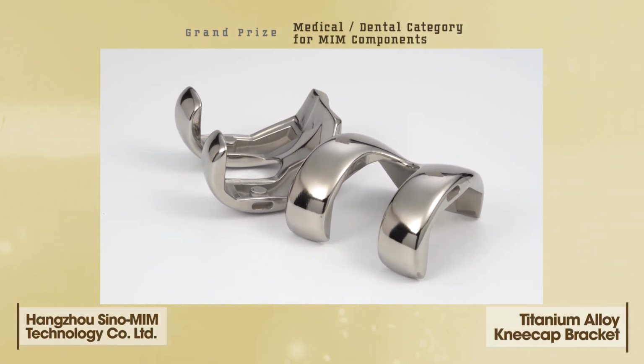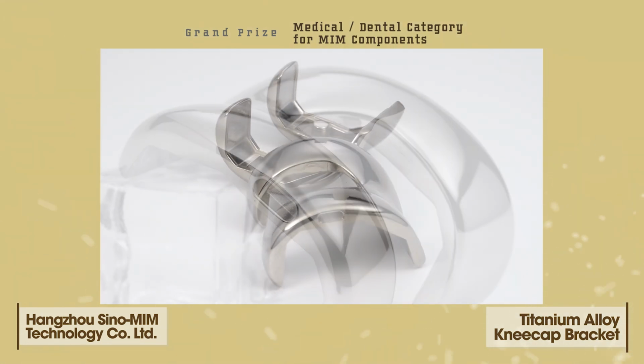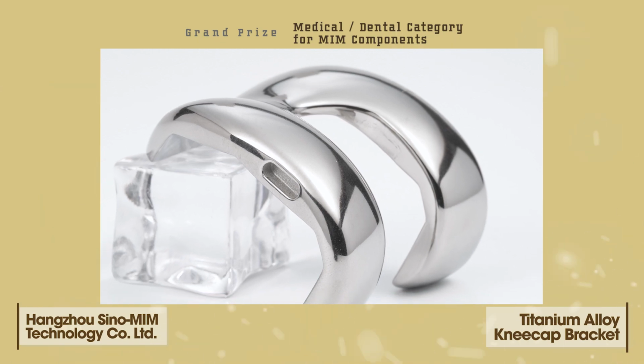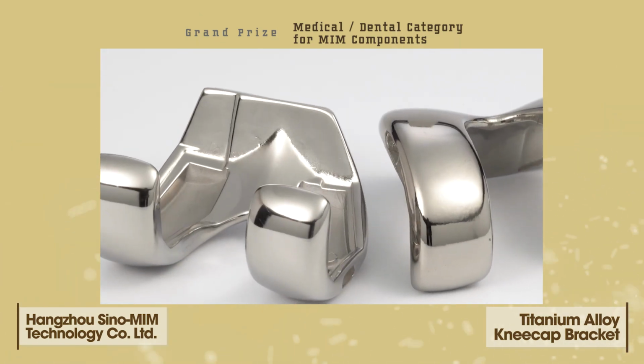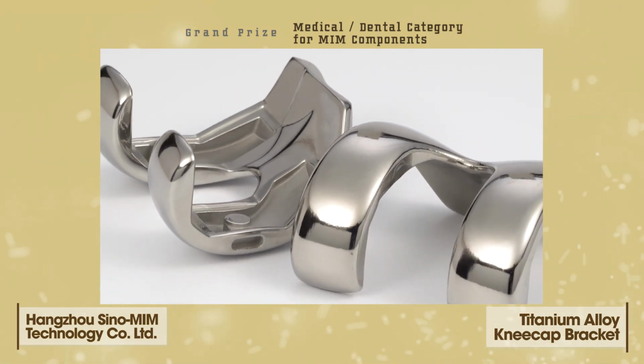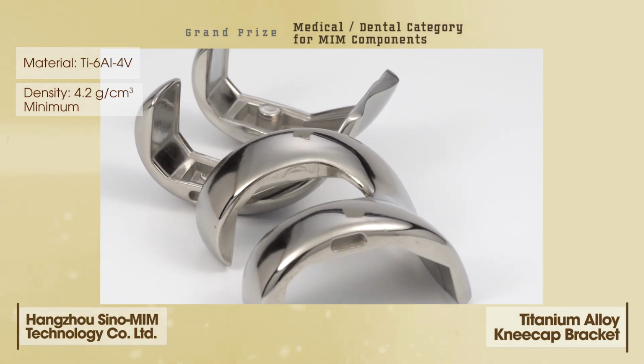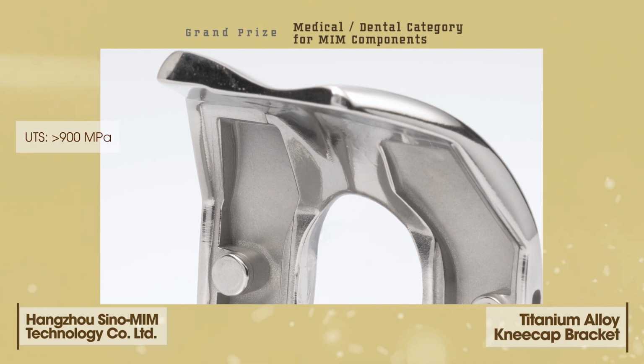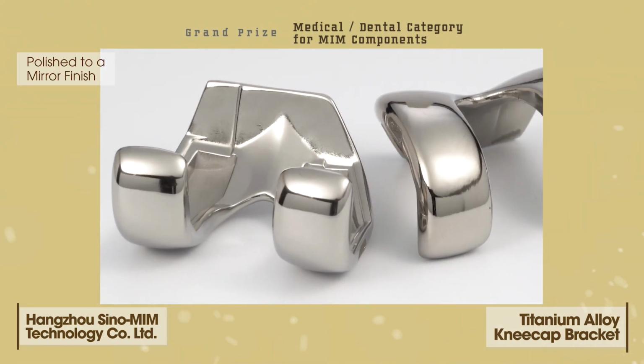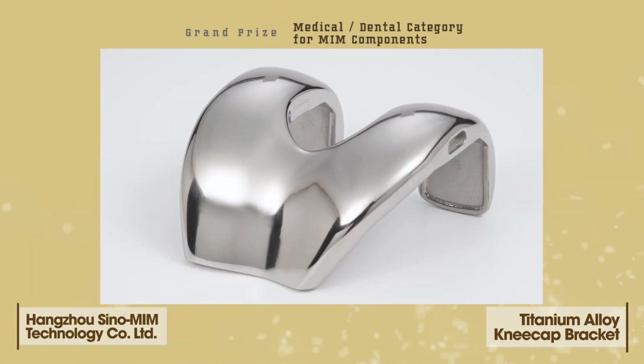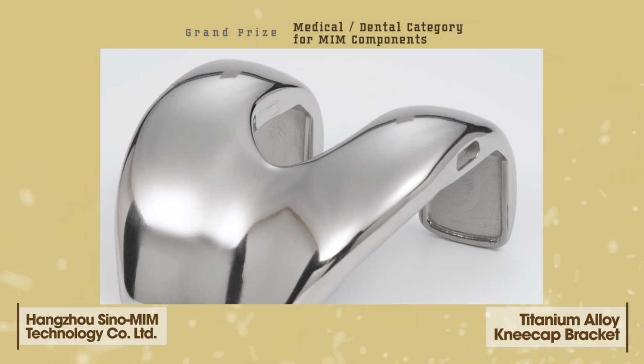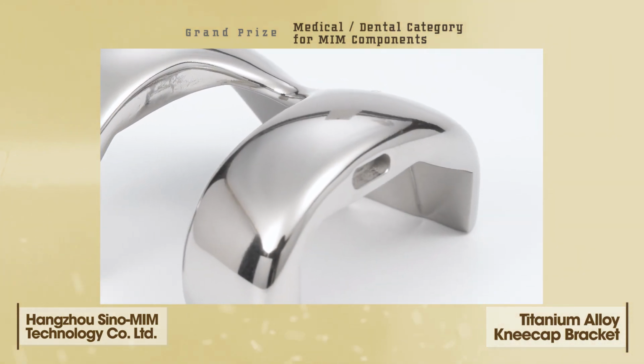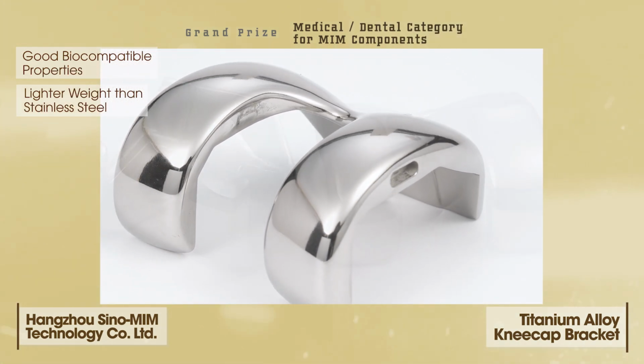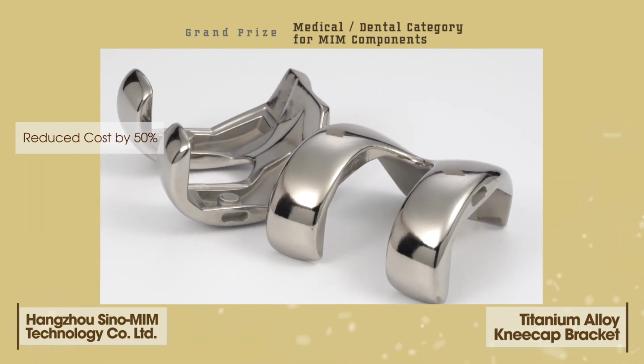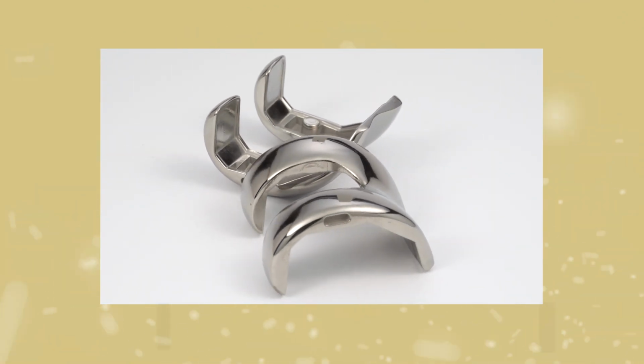Hangzhou Sino-MIM Technology Co. Ltd. received a grand prize in the medical, dental category for MIM components for a titanium alloy kneecap bracket. This titanium alloy kneecap bracket is used to repair or replace a human kneecap. The part weighs about 74 grams, nearly half the weight of a traditional stainless steel kneecap. Additionally, some patients have endured adverse effects from stainless steel kneecaps when used over a long period of time. The parts have a density of 4.2 grams per cubic centimeter and a tensile strength greater than 900 megapascal. The surface of the parts is polished to a mirror finish to provide superior wear resistance. Traditional stainless steel kneecaps are made using computer numerical control machining, have long lead times, and are very expensive. MIM has reduced the cost by about 50%, solved supply chain concerns, and the titanium alloy kneecap has good biocompatible properties and is much lighter.